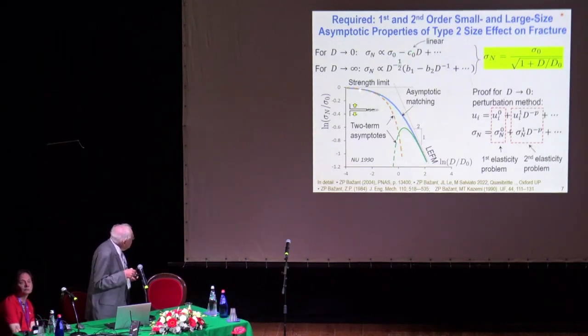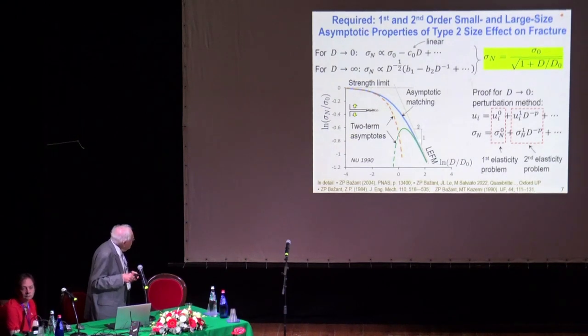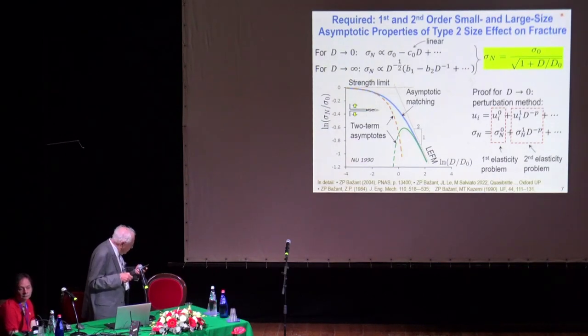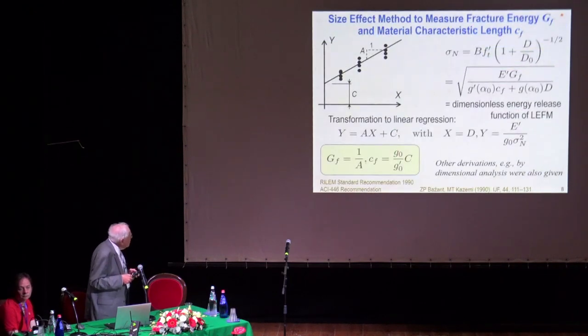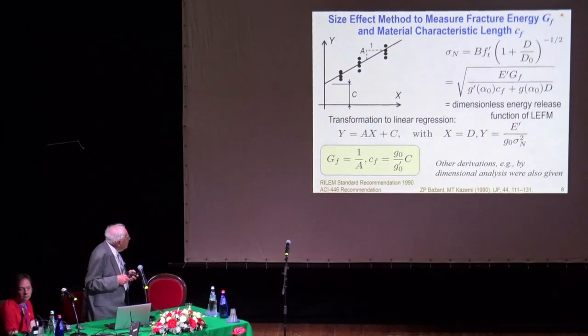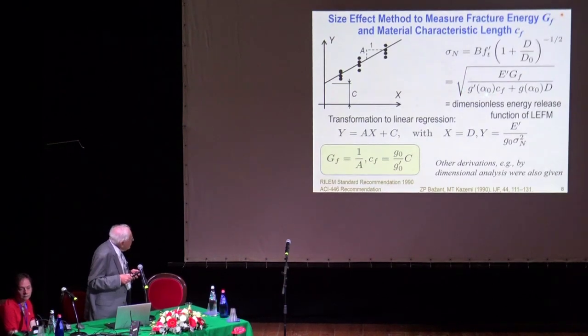Now, asymptotic matching means to find a smooth curve which has two asymptotic properties here, two there. This formula actually matches these two asymptotic properties. So this is, of course, a fundamental way to do that. And there are also other ways to obtain this. Now, the advantage of this formula, called size effect law, is that it can be related to the asymptotic expansion at large size, where g is the dimensionless energy release function, and this is its derivative, a is the length of the notch at failure, or length of the crack at failure. This is size D, this is the material characteristic length, elastic modulus, and fracture energy.